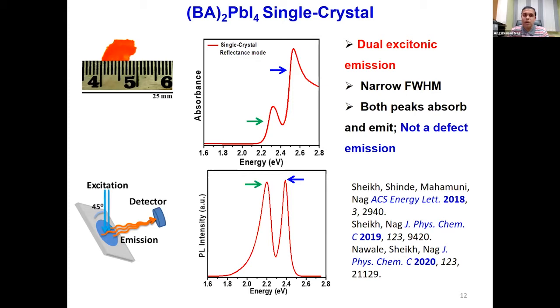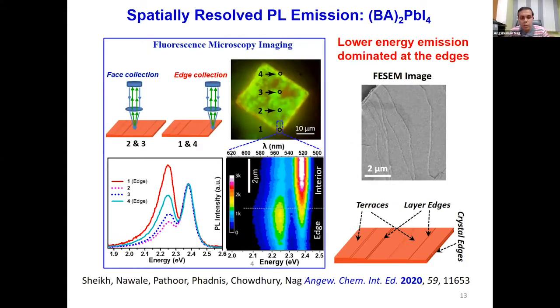To understand the origin of this two excitonic emission, we collaborated with Professor Arindam Choudhury from IIT Bombay, and they did spatially resolved photoluminescence emission. This is, for example, a fluorescence microscopic image of a piece of one such crystal, and you can measure the emission spectrum at different points, like 1, 2, 3, 4. If I collect the spectrum at these locations, presented here, you'll see that for all the spots we see two kinds of emission peaks. However, when you go to the edges, like spot 1 or 4, we see that the intensity of the lower energy emission is higher and higher.